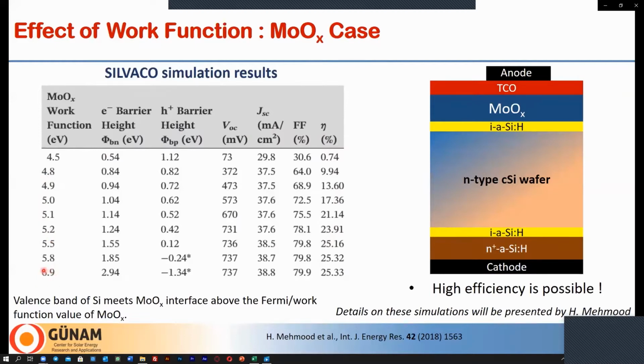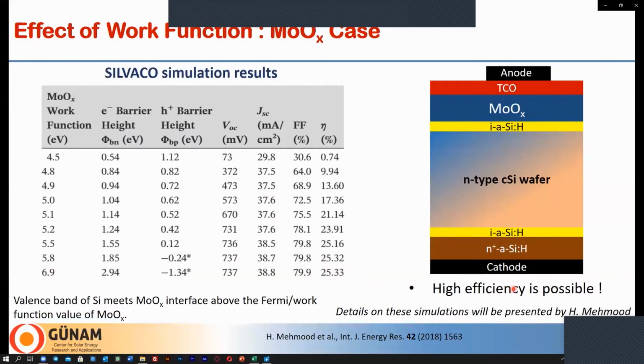By the way, this is the theoretical limit of the work function of molybdenum oxide. And with this structure, simulation shows that high efficiency of above 25% is possible. And I invite you to listen to a presentation about this work by Dr. Haris Mahmoud later today. So with this motivation, we studied molybdenum oxide experimentally. But before we proceed into